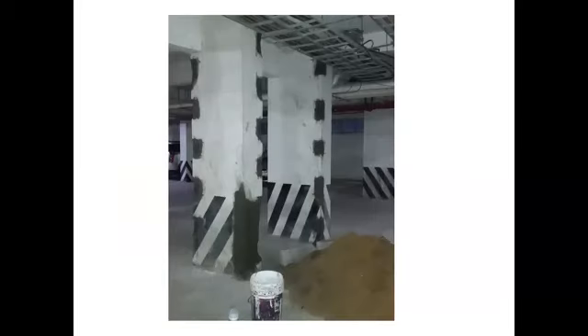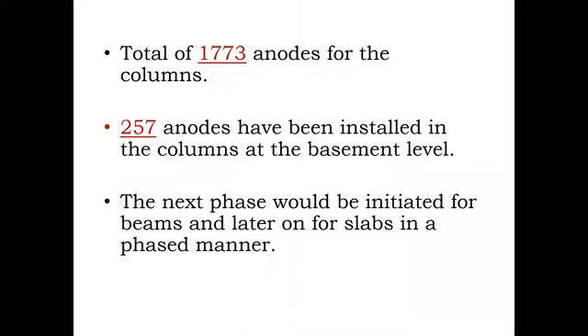You can calculate the spacing based on the steel density ratio as already explained by Professor Raji sir, and then you can monitor this also. In this particular case, we don't have to go for any test like a Profometer survey, core cutting, or UPV. Nothing is required. It is very clear. The water which has been used contained chloride. So what we want to check is the chloride content in the concrete at present, whether within the permissible limit or not.